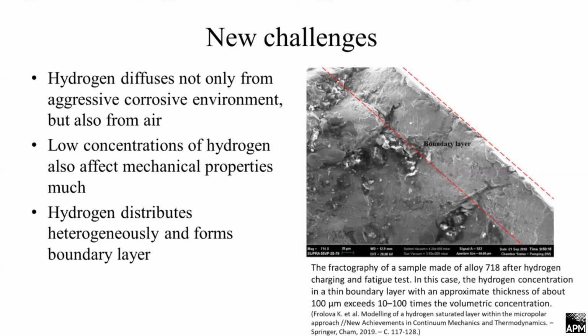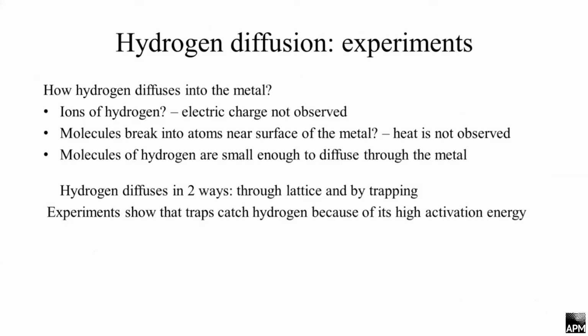I'm working in a huge team on this problem, and my challenge is to explain the formation of this boundary layer using diffusion models. So, starting again with the experiments: how hydrogen diffuses into the metal. There are a lot of models saying that ions of hydrogen diffuse, but experimental results show that electric charge on the surface of the metal samples is not observed. So it's not an ion of hydrogen. Also, some models say that molecules of hydrogen break into atoms near the surface, and then atomic hydrogen diffuses. But the heat which this would produce is not observed.